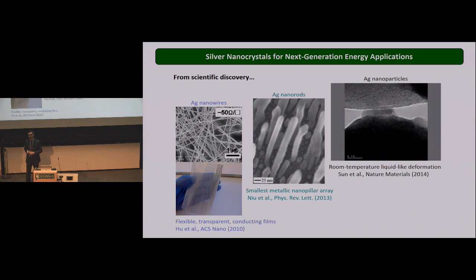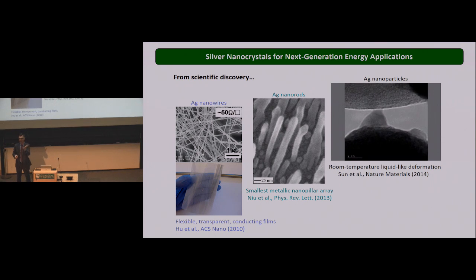But you also have an effect on your surfaces: the tendency to be flat or rough should depend on temperature, shouldn't it? On the atomic scale. Absolutely. So the comment is that the surface morphology changes with the temperature, and in fact, what makes the morphology change are those crystal slips. They form steps, and you see the wire, which is initially circular, is no longer circular after a few percent. So there is some roughness just from the plasticity that forms at this scale. And the diffusion here is just there to smooth out the defects, right? If you do not allow for surface diffusion of atoms, the steps are going to stay there and form a stress concentration, right?